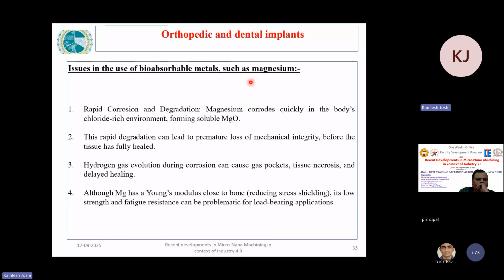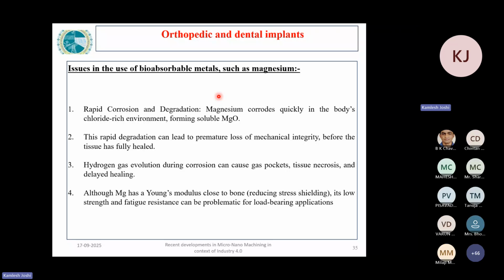So apart from these advantages, there are some issues in the use of magnesium as a bioabsorbable material. First, its rapid corrosion and degradation is one of the issues, which causes the formation of magnesium oxides quickly in the body. This rapid degradation can lead to premature loss of mechanical integrity before the tissue has fully healed. Another problem is the hydrogen gas evolution during corrosion, which causes gas pockets, tissue necrosis, and delayed healing.